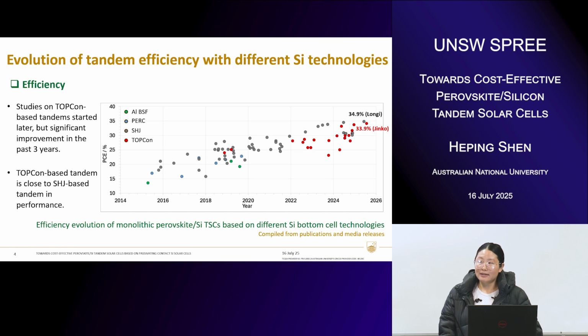If we look at the efficiency at the tandem level, here I show you an efficiency evolution of the monolithic perovskite silicon tandems based on different silicon technologies. And you can see it's very clear that the BSF and the PERC, which I mentioned briefly just now, which are the green and the blue color, are not much developed right now, not only because of the inferior performance, but also because of the challenges I mentioned in terms of integration into the two-terminal tandem. Silicon heterojunction and TOPCon both have been able, till now, to achieve high efficiencies in the 33 to 34 range, well beyond what silicon can achieve.